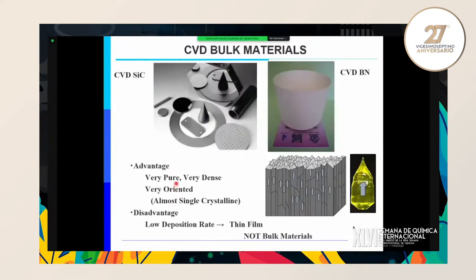So CVD is usually used to make thin films. CVD can also make very thick, very dense materials. Bulk CVD silicon carbide is used for many engineering applications. And also a bulk CVD boron nitride crucible is essential to grow single crystals.